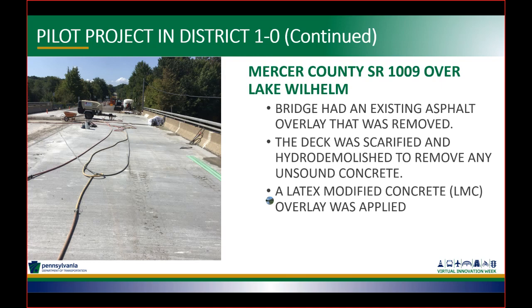So what the photo is showing you here on the left is we actually had to remove an existing asphalt overlay from the bridge. As I said before, the plan was to scarify and hydrodemo the existing deck surface to remove any unsound concrete. Once that was accomplished, we applied the LMC overlay, and that's what you're looking at in this photo, after that asphalt had been removed, the scarification and hydrodemo, and then the finished latex has been placed. And that's actually a distant photograph of them just beginning the removal necessary to build the link slab.